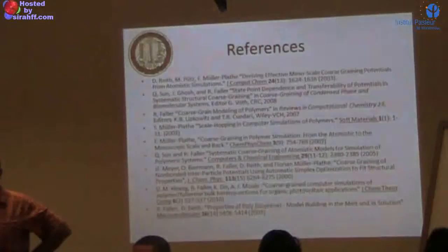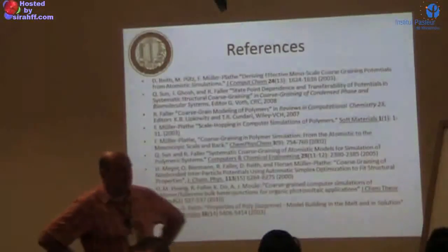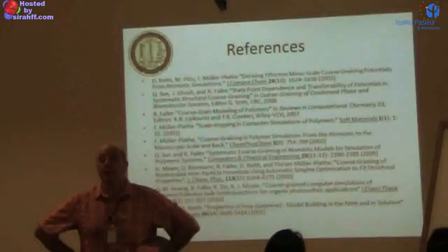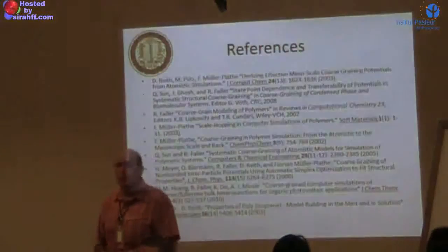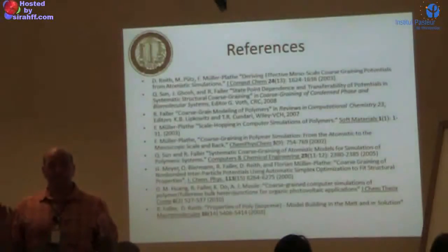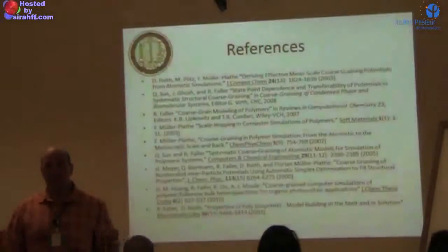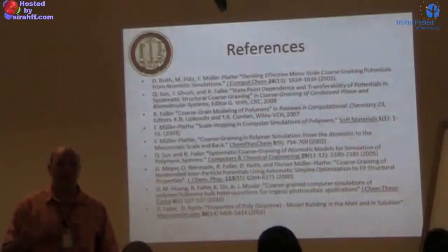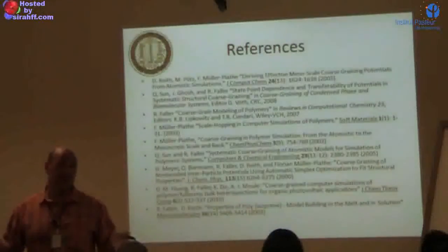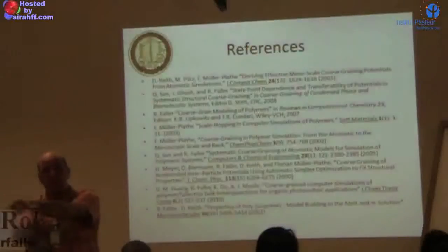There is a significance, especially between dihedral and non-bonded. Normally, say the bonds and the angles, they converge. That was actually the work of Faller, who really looked into things like that in detail. The point is that the dihedrals and the non-bonded are both soft, so kT is an important number in their case, whereas for bonds and for angles, it's not a big number, so it doesn't matter. But as the two are similar in size, what we often do is one non-bonded step, one dihedral step, one non-bonded step, one dihedral step.